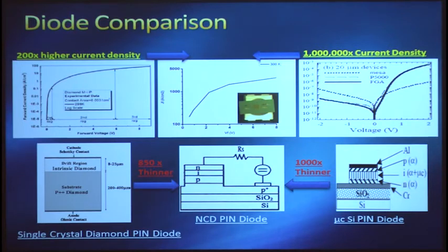What we actually noticed, though, from an economic standpoint, was that we can use approximately 850 times thinner layers of diamond to accomplish that function, and approximately 1,000 times thinner material than the silicon counterpart. So for the first time in diamond, we actually have a cost-effective way of manufacturing these diamond materials. We're able to marry it with the silicon platform, so it's not a seismic shift away, and we're able to go after a much broader market of applications.